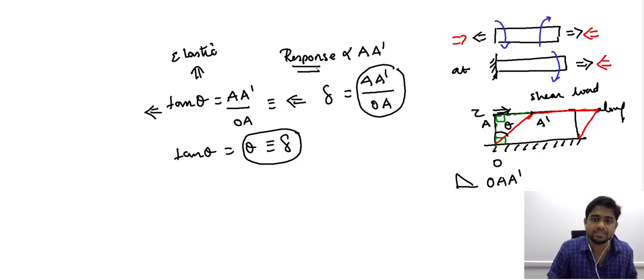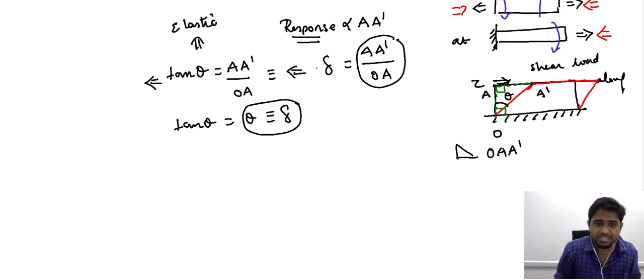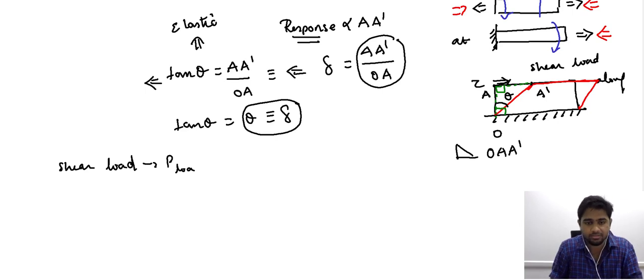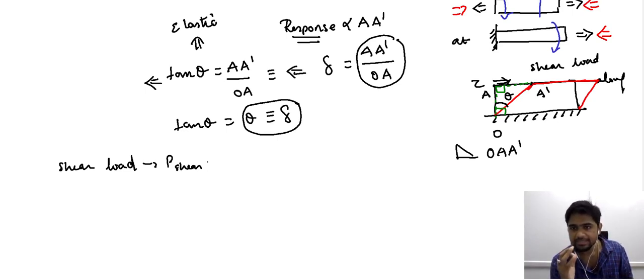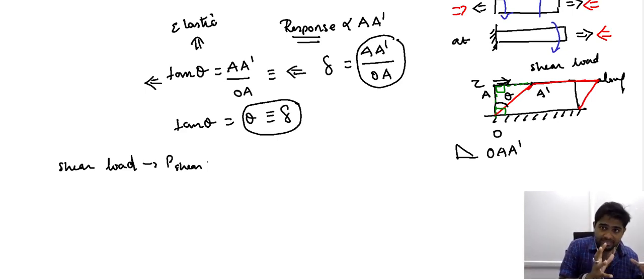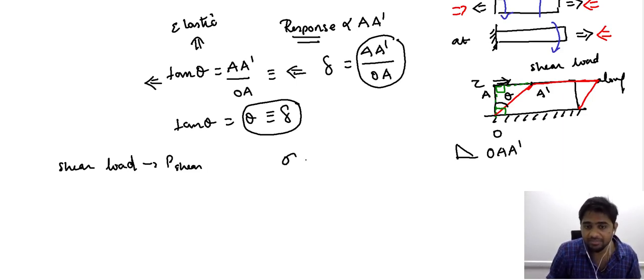Now what we have not considered is how we can describe the shear load that we have imposed. The shear load that we have imposed is nothing but the load that is applied on the surface. But again, we saw that when we are describing the mechanical condition in terms of load, when we want to use this load to describe the specific mechanical behavior, it is influenced by the dimension of the material. So therefore, while we were discussing compressive and tensile loading, we translated the load to stress, and this stress, we saw, is the ratio of the load to the cross-sectional area.